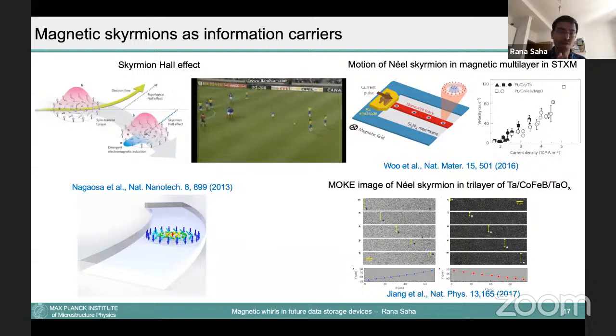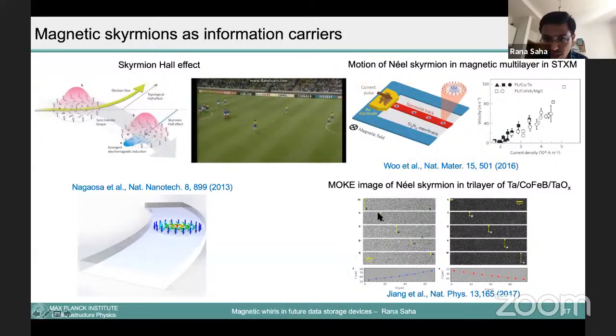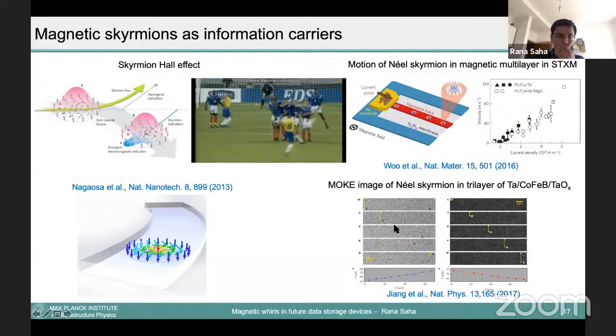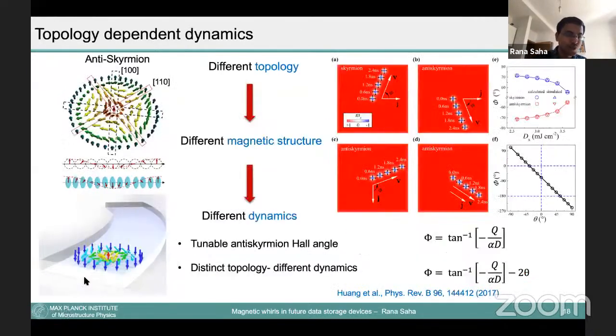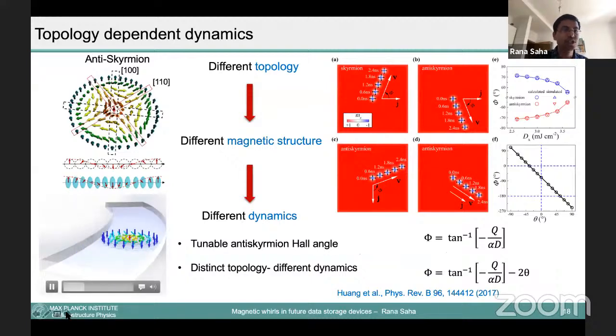But this is not good for real applications, because of the Magnus force, the skyrmion will hit the boundary of your device and you will lose data. You can see here, if you apply a force, the skyrmion moves in the transverse direction. It never goes in a parallel direction. So this is a disadvantage. To avoid this disadvantage, we use another structure called anti-skyrmion.